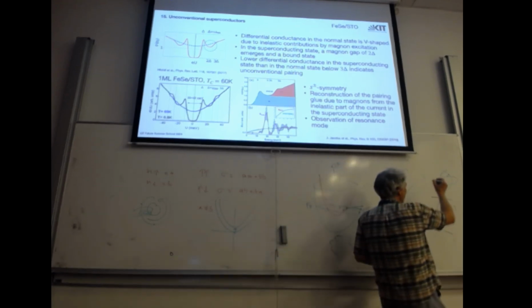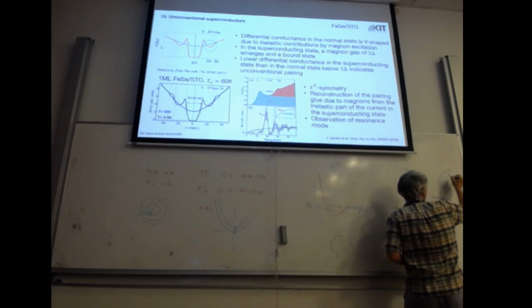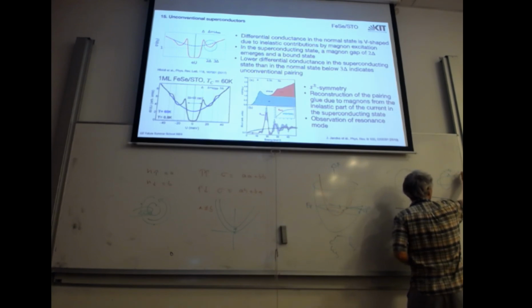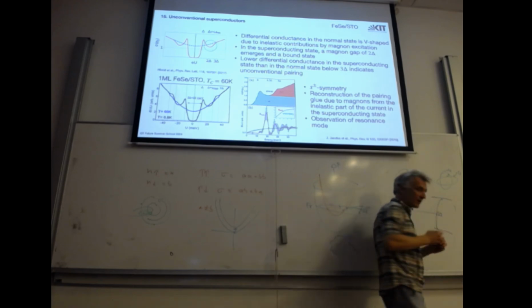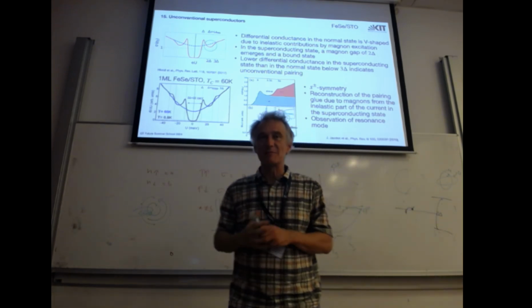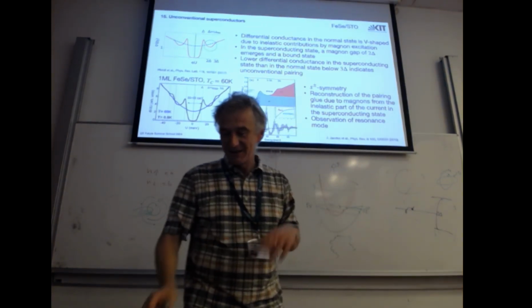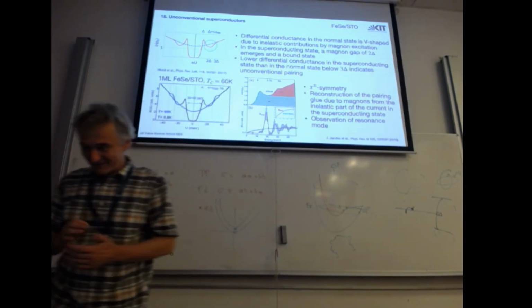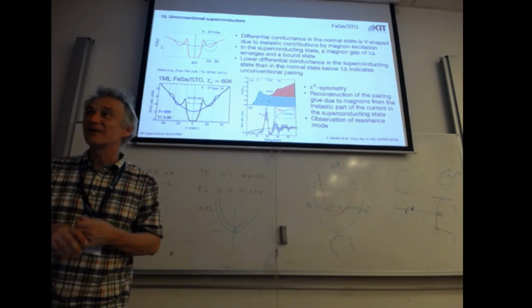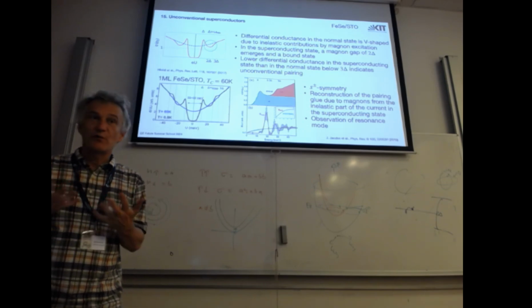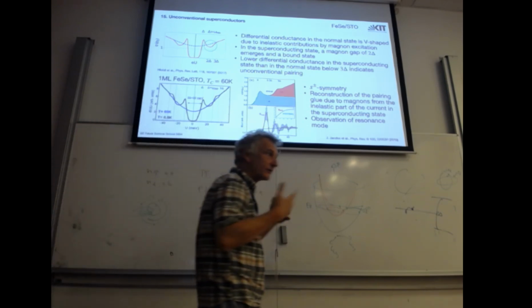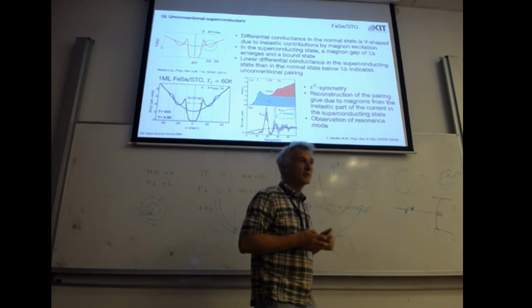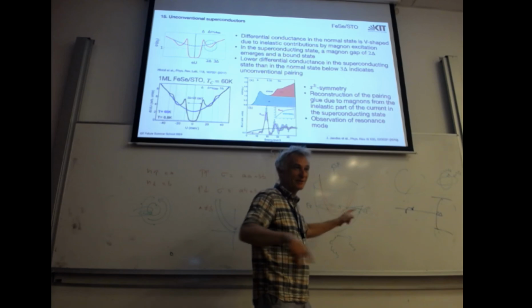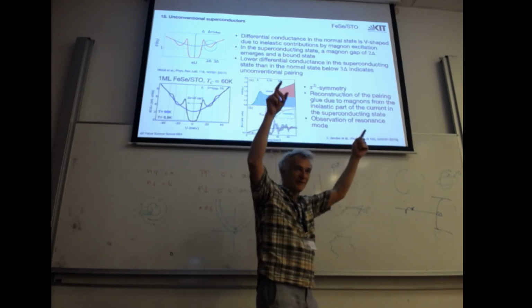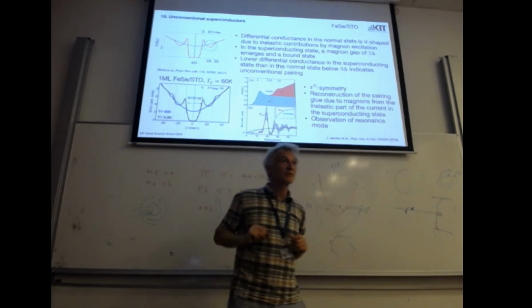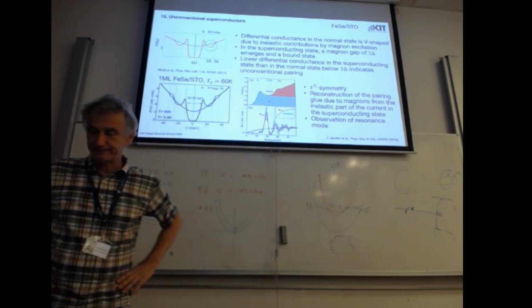And then the sign of the wave function is inverted. So the superconductor's order parameter is S plus minus in this case. Maybe a little bit difficult to understand, but you form pairs which are on different bands and they have opposite spin. The graph you remember, this time graph, the spin is flipped under the scattering process.